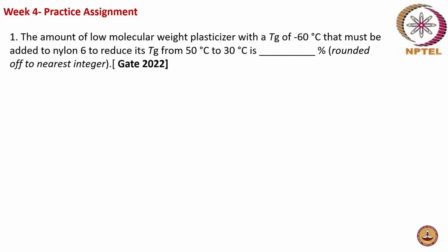So the first question for week 4 practice assignment is: the amount of low molecular weight plasticizer with a Tg of minus 60 degrees that must be added to nylon 6 to reduce its Tg from 50 to 30 degrees is dash. So we have to find out what is the amount of the low molecular weight plasticizer that is to be added so that we reduce the glass transition temperature of nylon from 50 to 30 degrees. So that above 30 degrees it becomes more flexible, compared to nylon 6, where it is above 50 degrees only that it becomes flexible. So this is the question.